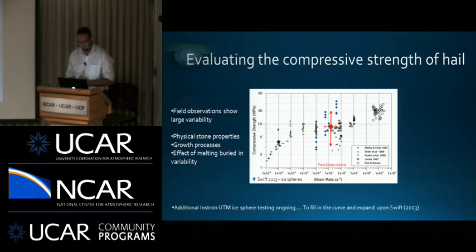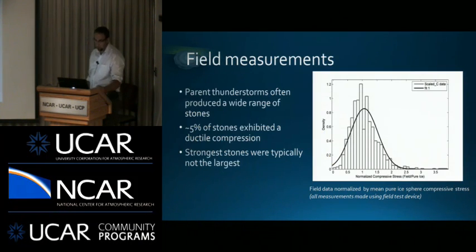But those are just kind of general bullets that you could start to work on. Now, if you scale that compressive stress by the mean of the pure ice information there, and look at the distribution, you actually get a mean where natural hailstones are about 6% at least a little bit stronger, but again, there's a lot of variability. Maybe the mean's not a best metric there, you use a median of distribution. But from individual events, you actually get a wide range of these values.